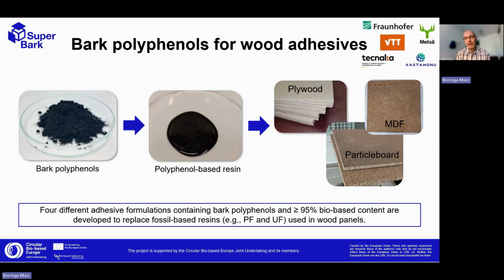And also each wood panel could have different requirements depending on the intended use, whether it's indoor or outdoor. The requirements for the adhesives and for the final products are obviously different. So we develop different types of resins that we test in the making of plywood, MDF and particle board. As I mentioned before, one of the targets of the project, which is in alignment with the requirements of the call, is to develop these formulations which are at least 95% bio-based. And the target is to replace fossil-based resins, mostly phenol formaldehyde and urea formaldehyde resins, which are the benchmark reference adhesives or resins used in this type of panels.